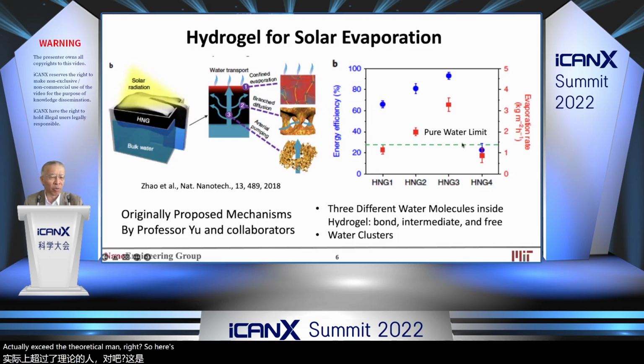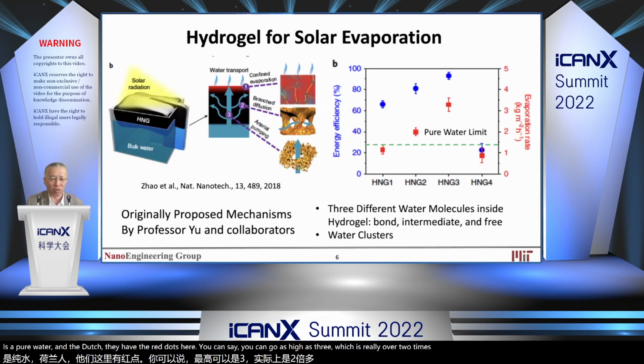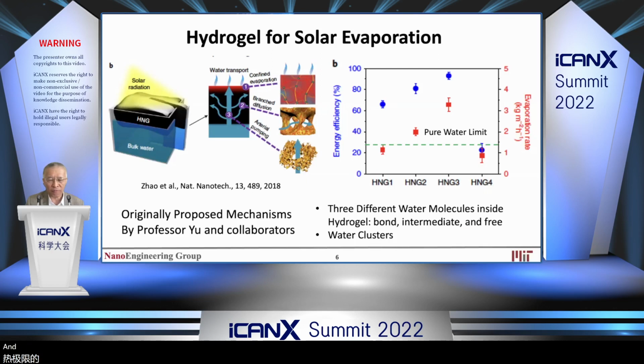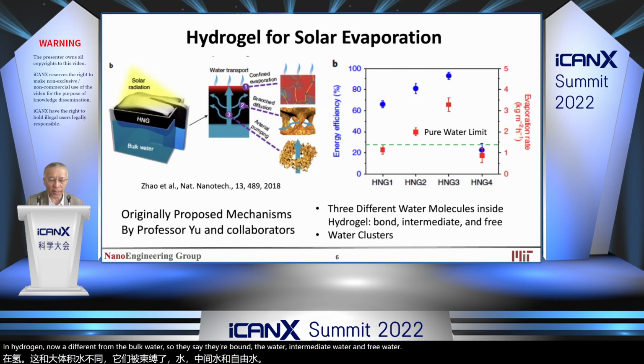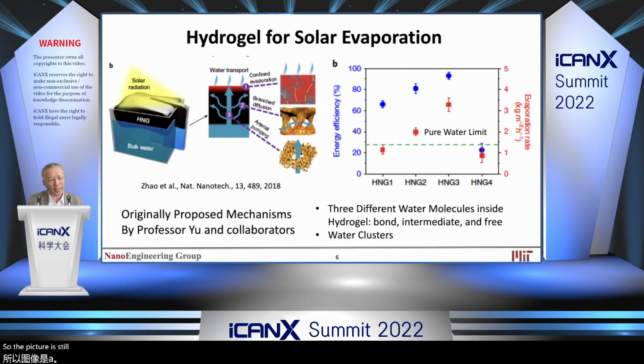Here the green line is pure water, and they have the red dots here. You can see it can go as high as 3, which is really over 2 times the thermal limit. Professor Yu and their collaborators proposed this is probably because water in hydrogel is different from bulk water. They say there is bound water, intermediate water, and free water, and they also mention the possibility of water clusters. So their picture is a reduced latent heat, and with that they calculate an efficiency still less than 100%.